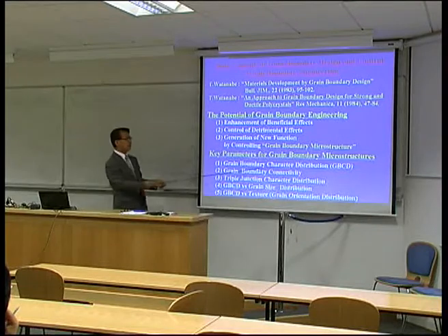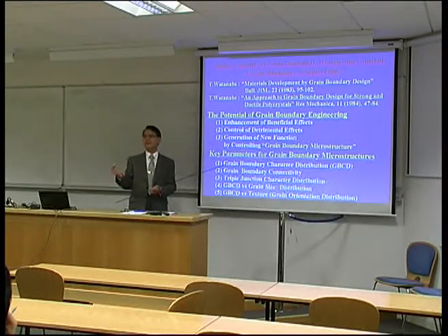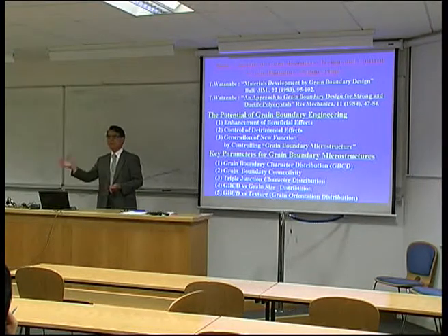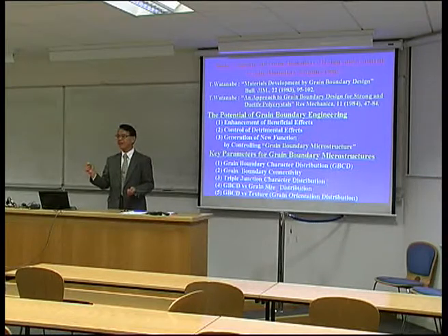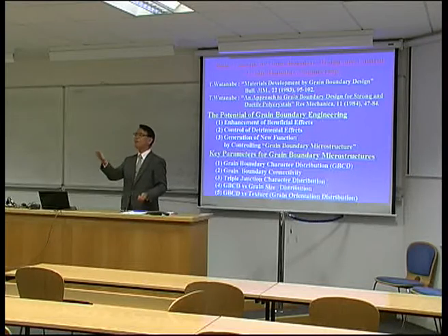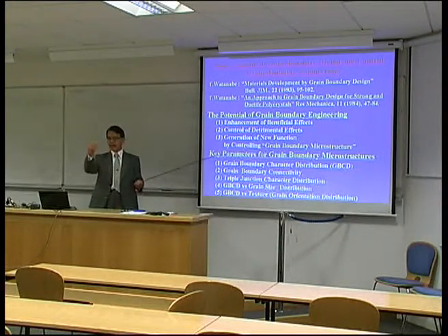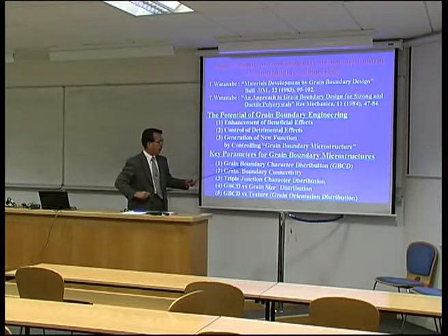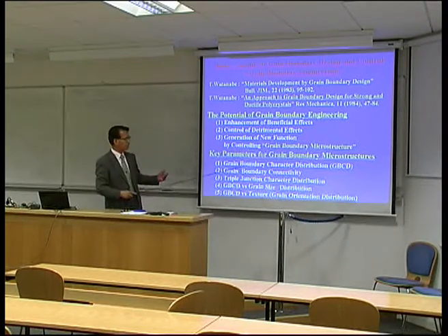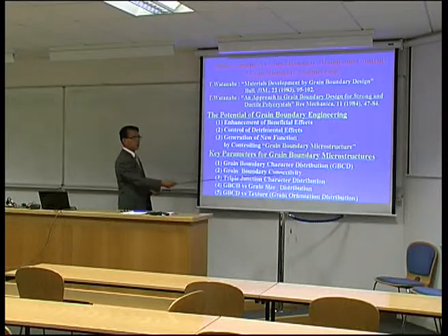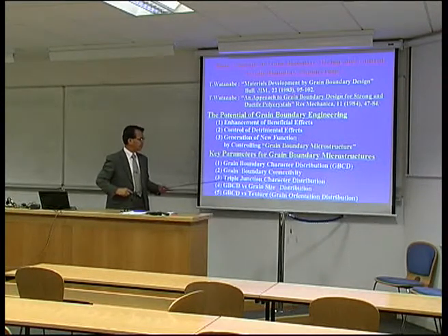Firstly, the grain boundary character distribution. Actually, this parameter was proposed by myself in 1981. Since that time, many people have gradually been using this parameter to control grain boundaries in polycrystalline matter. Nowadays, GBCD has become more popular, and I am very pleased with this situation, because this is very important. Not only the boundary density and grain size, but by taking this parameter, we can take into account the structure-dependent properties of the grain boundary. Secondly, as I mentioned, grain boundary connectivity is also important. And also recently, many people have recognized the role of the triple junction.